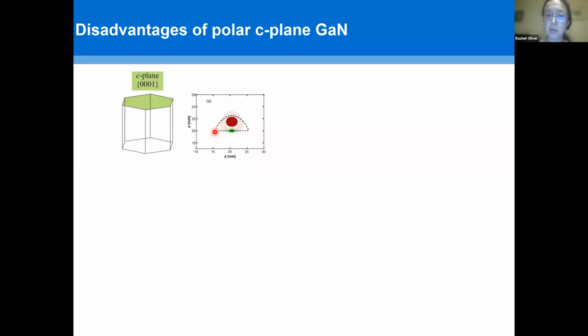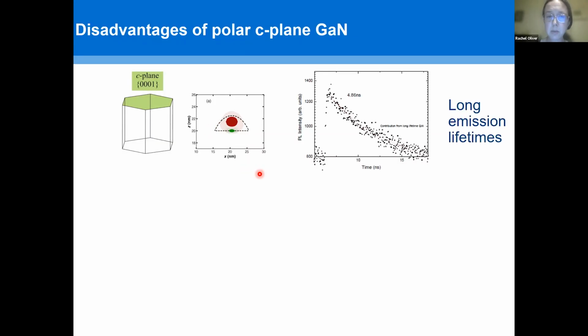This is a simulation from Stefan Schultz's group of one of our quantum dots. And the consequence of that is, because the electron and hole are pulled apart, their wave functions, electron wave function in red and hole wave function in green, don't actually overlap all that well. And that means that it takes a long time for the electron and hole to recombine with one another. And we get long emission lifetimes. Now that just limits how many single photons you can have per unit time. It limits the transmission rate of data on your single photon source.